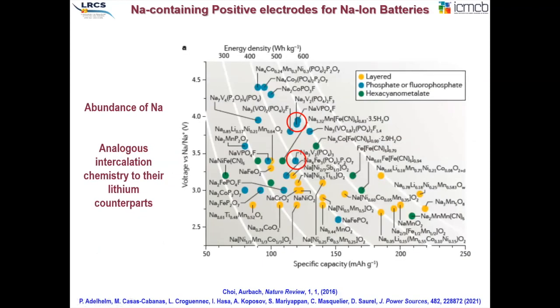If we look at the global picture of sodium ion battery cathodes, there are plenty of materials, compounds we may think of. And you are all familiar, I guess, with these voltage capacity plots. Just to mention that polyanion materials are in this range of energy densities, close to 400 to 500, if we consider the Nasicon type and NVP versus the NVPF type of family of materials, which show higher voltage with more or less similar global capacity. The layered oxides Jerry talked about have bigger specific capacities and some of them very nice voltage ranges, which basically leads to higher energy density for the layered oxides.